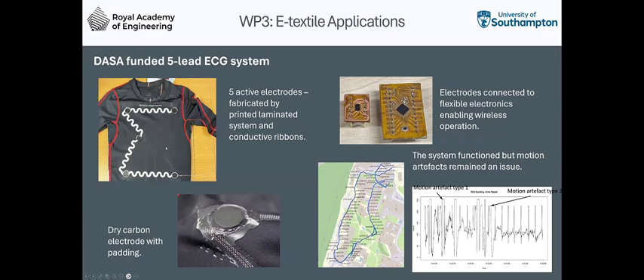I showed this earlier. This is a 5-lead ECG vest, and we came up with this wiring interconnect solution. And this just shows the electronics that goes with that device integrated within this shirt. And this shows the route someone took around the university campus, monitoring the heartbeat. We ran out of time with this project to really finish it nicely, but it did work, but you do get motion artifacts. I think this is when you're going upstairs, for example, the electrodes move against the skin and you lose the signal. But once you're walking normally, the signal comes back. So it did show that we achieved a nice working 5-lead ECG system, but we do have to remove the motion artifacts.